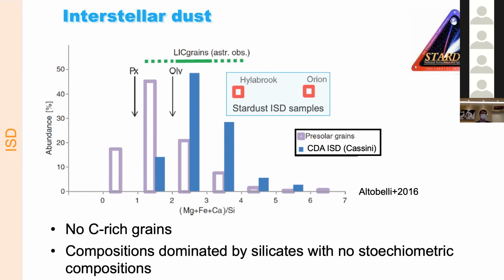But the most abundant pre-solar grains, even in meteorites, are silicates. And you see that in this diagram, the composition of these silicates is not stoichiometric, and as expected, because it's amorphous. So there is a range of composition, but so far no precise composition.